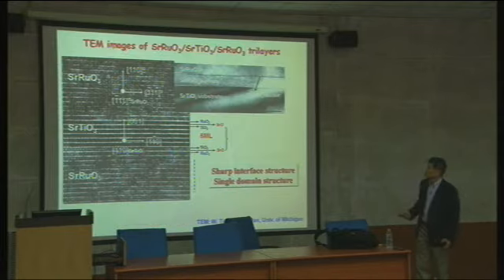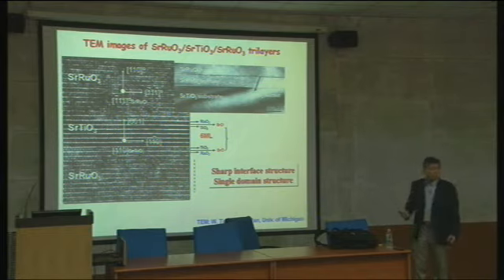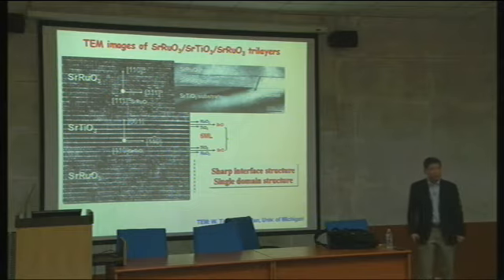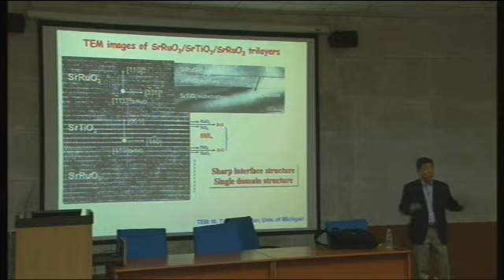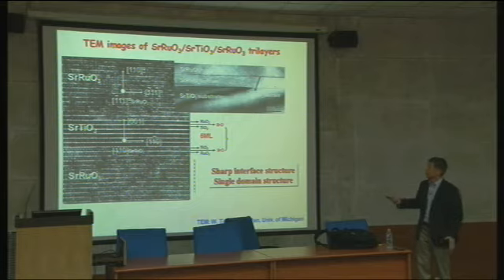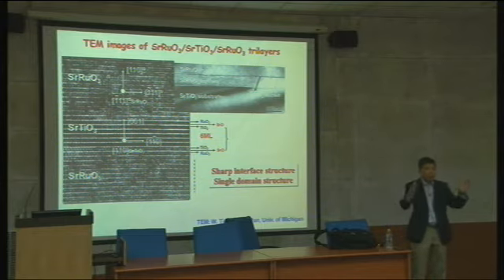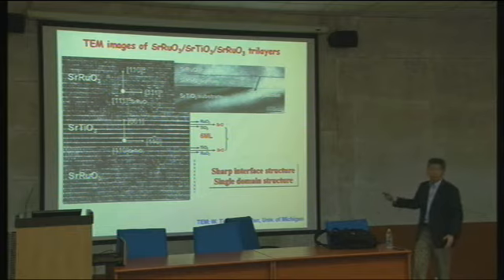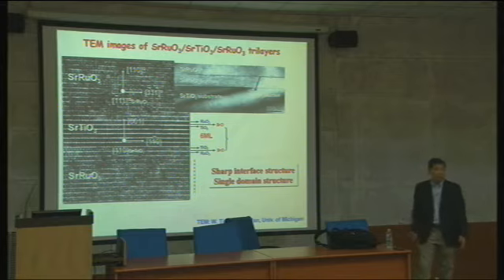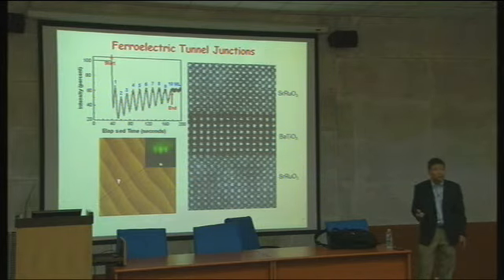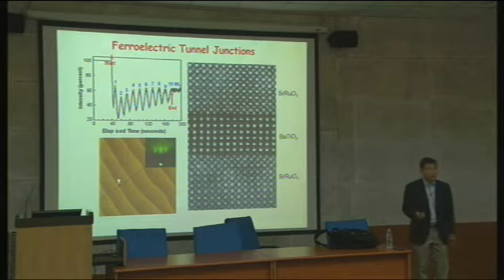And then when you look at the cross-sectional micrograph, all layers are perfect single crystal. And you can see there are no grain boundaries and no dislocations, which means fully coherent. And the lattice parameter of strontium ruthenate is larger than strontium titanate, so it grows biaxially compressed, and grows like this. And then a very thin layer of strontium titanate is sandwiched between here, and you can see that it is completely single crystal.